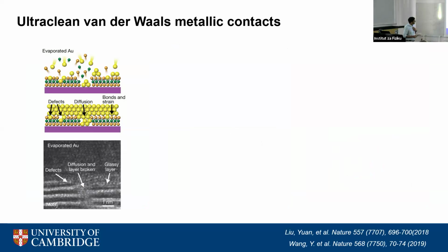And this is a TEM image. You can see that it really goes through the material. And what these defects do, they pin the Fermi level. You're no longer free to use the Fermi level of the metal, but rather you have mid-gap states between the metal and the semiconductor. And these defects are very prominent for 2D materials specifically because in bulk materials, you have an interface and then you have the bulk. But in 2D materials, you don't have a bulk. The surface is kind of the whole material. So if you damage the first layer, then you have nothing left.